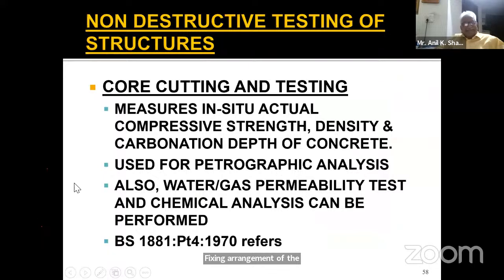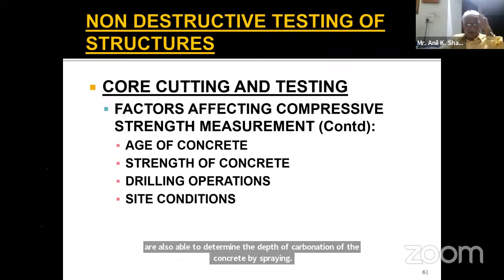Core cutting and testing measures in situ actual compressive strength and density in the laboratory. We carry out the compressive test in the laboratory, and we arrive at the actual compressive strength of the core. We are also able to determine the actual density of the concrete. We are also able to determine the depth of carbonation of the concrete by spraying the phenolphthalein indicator.